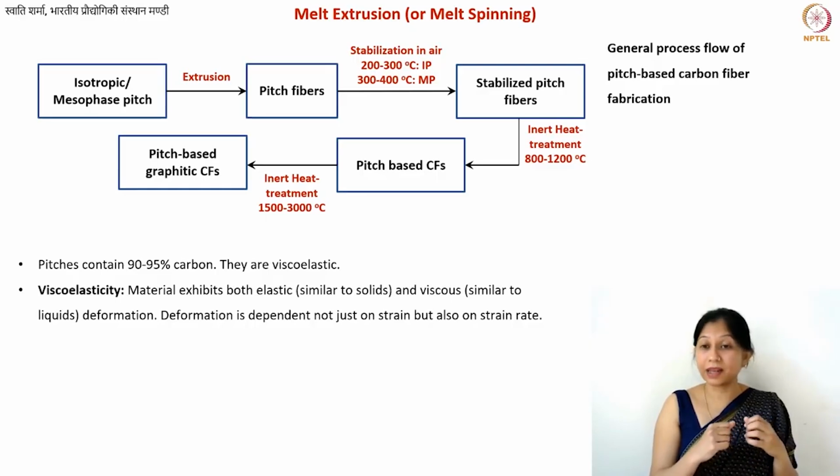Similarly, in the case of semi-crystalline materials or liquid crystal-like materials such as mesophase pitch, you know that there are certain parts that are crystalline. These crystalline parts behave like solids and they can offer elasticity, while the liquid-like parts will offer resistance to flow. So that is why you have a combination. And that combination can, by the way, be very complex.